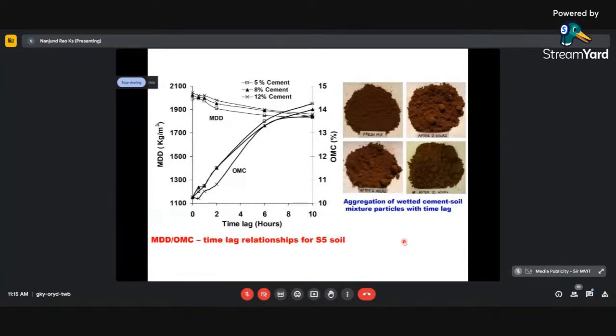Now, this is a graph which talks about a combination of the two, that is maximum density on the y-axis on the left side, and the y-axis on the right side is OMC. Trying to combine these two things, how after a time lag, that means after we add water and just leave it, don't immediately do anything. For example, the picture you see, fresh mix, that is how the mix looks immediately. Then after 2 hours, you have added a stabilizer, water is added, therefore a lot of lumps will be created. And the slide with 4 hours, you can see more lumps, and after 10 hours.